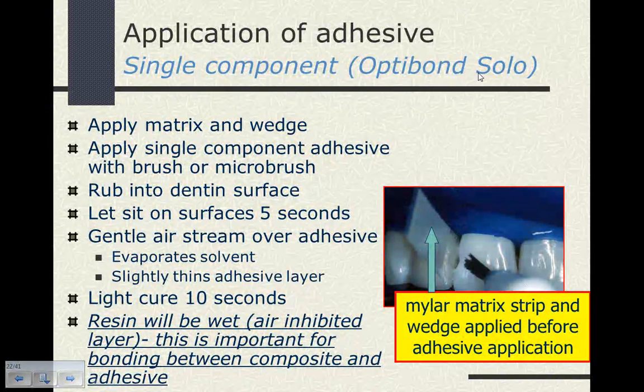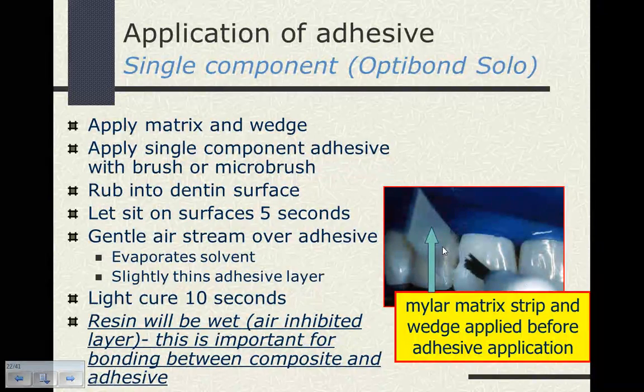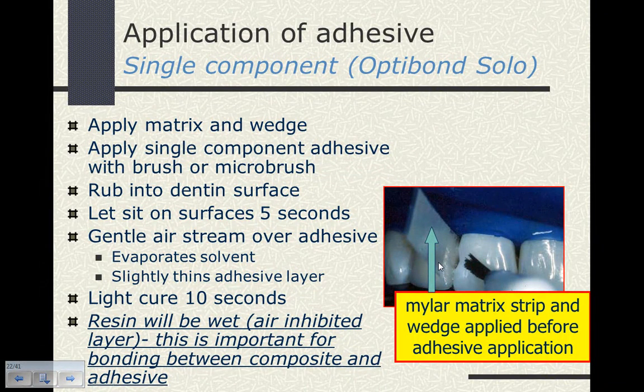Applying our adhesive, and here we're talking about a single component adhesive, the Optibond Solo, for class 3, we're placing a mylar strip in between the teeth supported by a wedge. We apply the matrix and wedge, then we paint in the single component adhesive with a brush or a micro brush. We rub it into the dentin surface and allow it to sit on the dentin surface for 5 seconds. We use a gentle airstream over the adhesive, which evaporates the solvent. It slightly thins the adhesive layer, and then we light cure the adhesive. Once the adhesive is light cured, it will be wet, and that's the air inhibited layer, and this is an important layer for bonding between the composite and the adhesive. And this is a review of something that you learned in the first year.